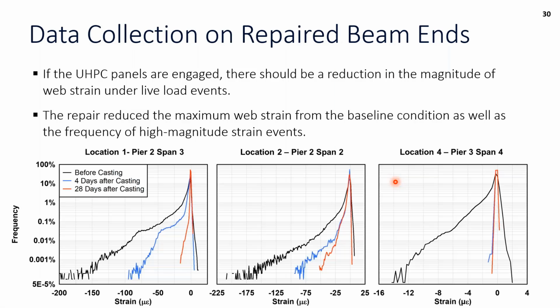And to show that we were getting the performance that we expected, we looked heavily at our data collected on the repaired beam ends at different locations. There are two main things that we were looking for. The first is if we're engaging those UHPC panels, and we did do instrumentation before the repair and after. So we wanted to see a reduction in the magnitude of web strain under live load events. And we really wanted to see that shift. So when we're getting that truck passage, how much strain is going into the web.